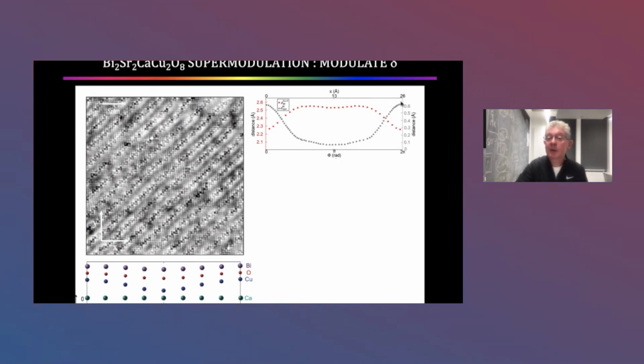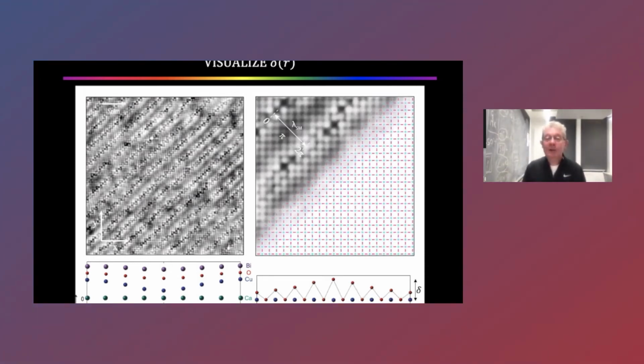The gray dots on the top right-hand side tell us the location of the bismuth atoms in the top layer. But from X-ray scattering, we also know what's happening to the copper to apical oxygen distance inside the crystal. So when the bismuth atom is at maximum displacement along these squiggly lines here, then the apical to copper atom distance is minimal. And when the bismuth atom has minimum displacement, at what we call phase pi here, then the apical distance is maximum. So everywhere in this picture, by using X-ray refinement, one could know in principle how big the apical distance is between the apical oxygen and the copper atom. And we have enough precision to know that for every atom in this field of view.